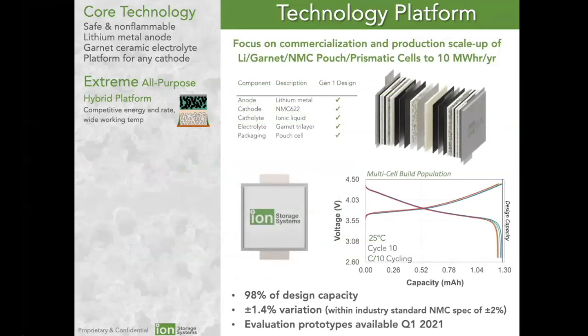This is the one slide of some of the data for the NMC cells that are being made by the company. We're now currently scaling these things to 10 megawatt hour per year production levels. You can see the data for the pouch cells, the number of cycles and repeatability between cells from this more of a manufacturing process. And we do plan on having prototypes available sometime Q1 of 2021 for a variety of interested partners.